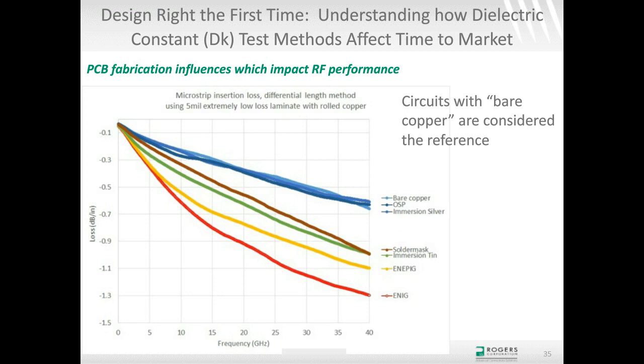ENIG is typically the highest loss. Every time I've done a study on a lot of different materials and thicknesses and designs, ENIG is always the highest loss finish. And it really is a good finish. It's just that it does affect insertion loss. So my comment here is ENIG's fine to use because it really does have a good track record. It's used a lot in the industry. It's very reliable. But as long as you understand there's going to be more losses and you account for those losses, then that's most of the battle right there.